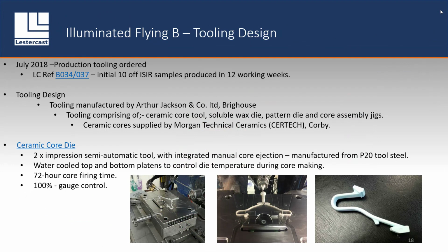So going back to the production side of things, Martyn's mentioned the core. So not only was there a wax tool, a soluble wax tool, but there's also a core tool as well. Production tooling was ordered in July 2018, and the first of 10 samples produced in 12 working weeks. Arthur Jackson and Co in Brighouse produced the tooling, which is the ceramic core tool, the soluble wax die, the pattern die, and also the core assembly jigs, which we'll show you a little bit later.